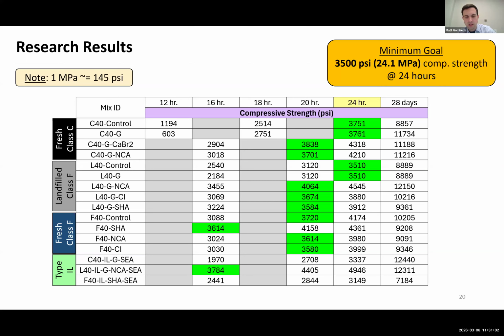An average of 3 cylinders here gets us the results in the table. And then for all of the other mixes, most of them anyway, we were able to hit our goal within 24 hours and a lot of them within the 20-hour window. And we're not using any heat to accelerate the mixer. It's purely based on the mix design optimization and the accelerators.